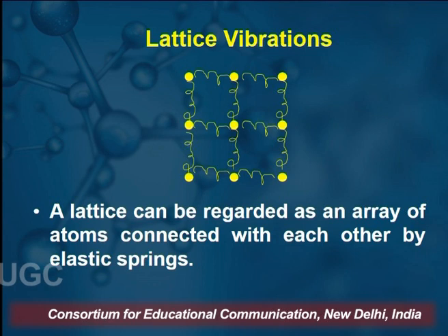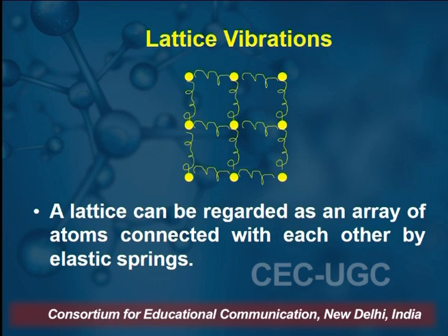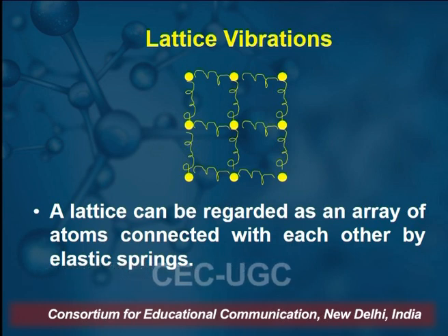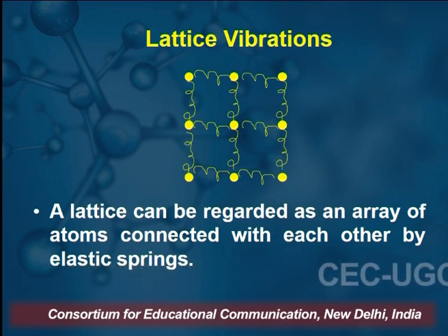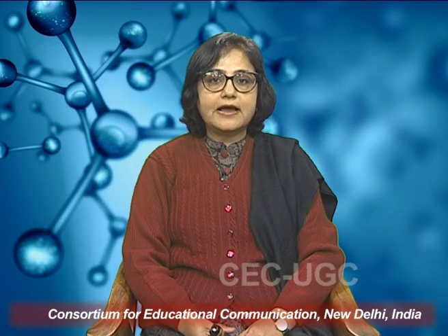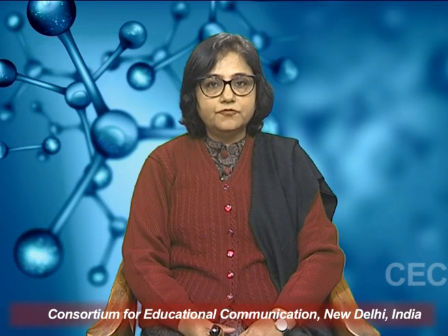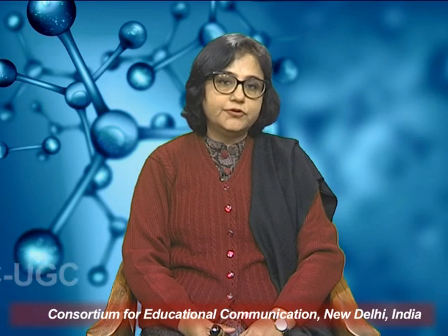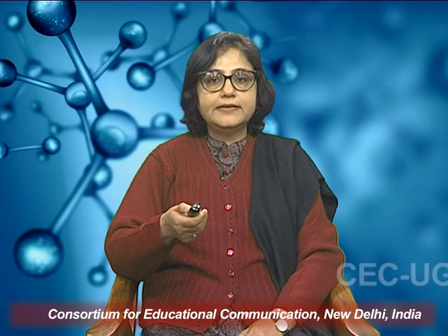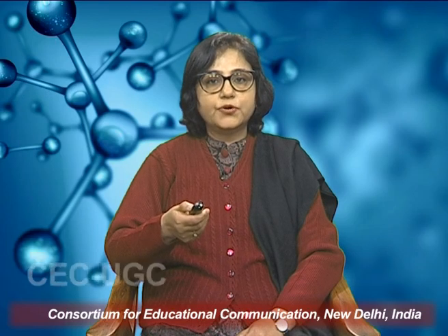These are not real springs that are there. These are the springs that we presume are there within the lattice, because any disturbance that is produced in the lattice, any force that is applied at one end, is propagated through the entire lattice, and the waves that propagate in the lattice are sound waves. These sound waves are quantized and they can have values of k equal to pi by L, 2 pi by L, 3 pi by L and so on and so forth.